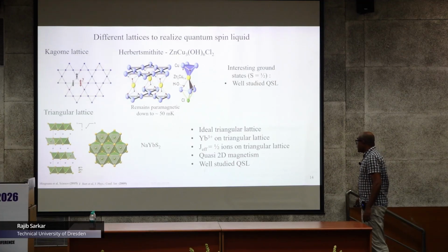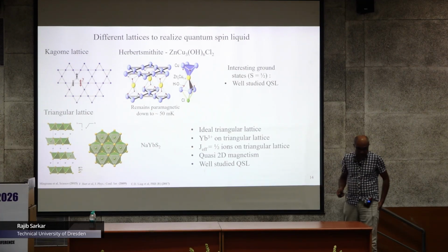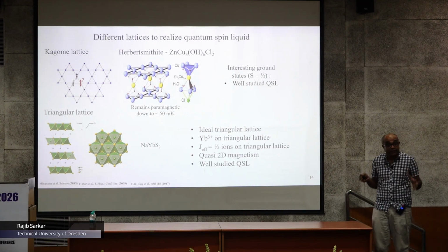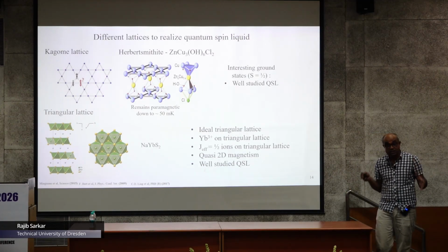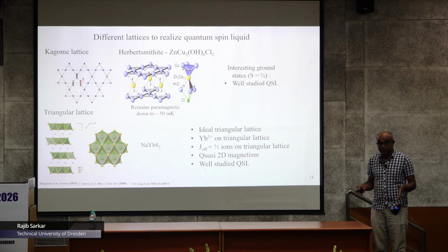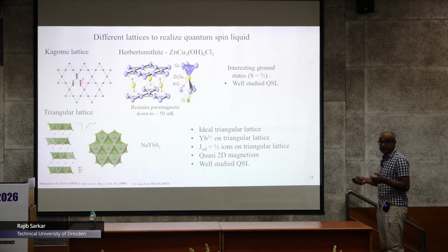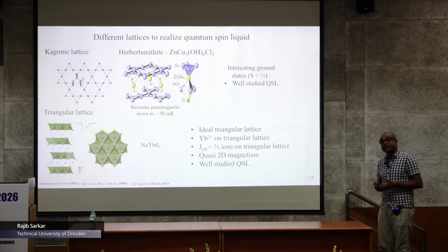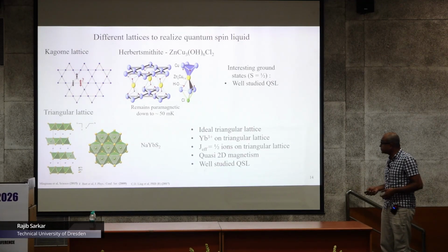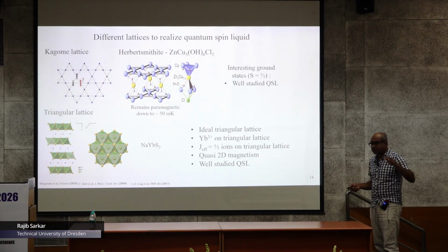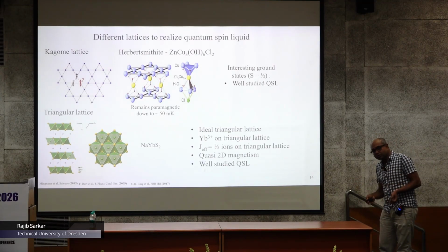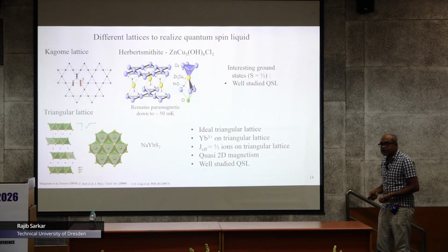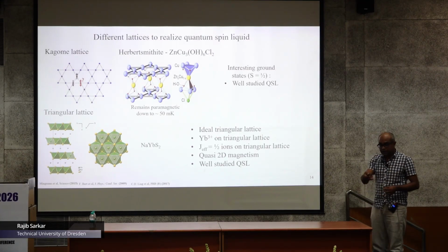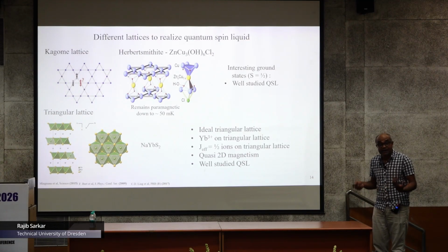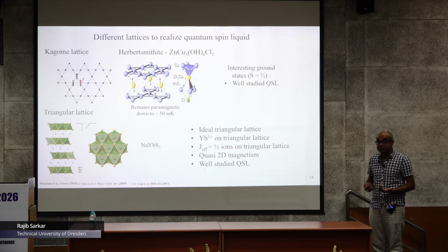Okay, so as far as quantum spin liquids are concerned, there are several systems that have been targeted, and basically some detailed investigations have been done, like zinc copper Herbertsmithite. A lot of experiments have been done. That is an interesting compound, a spin S equals one half system. And then we also discovered in Dresden sodium ytterbium sulfide 2. This is also quite interesting, but it's a triangular lattice. And we saw also the pyrochlore, and also today Moik showed this holmium based metallic system in proximity to the quantum spin liquid state.